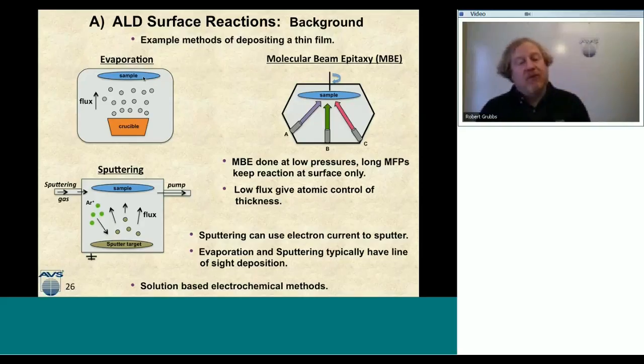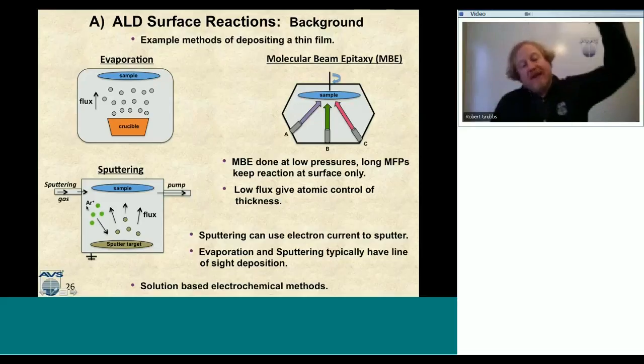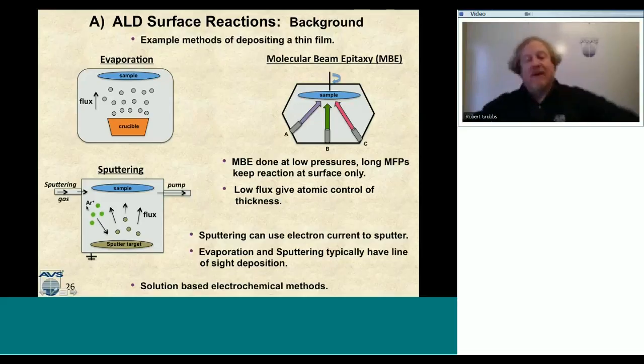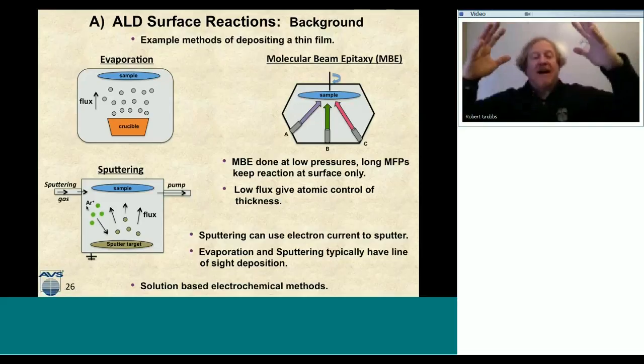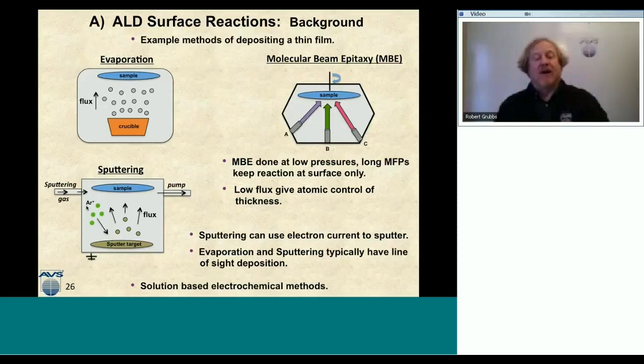Another similar method to that is sputtering. And sputtering is sort of a more aggressive method of evaporation, where we'll have a sample mounted on the top, and we actually have sputtering targets that are made of certain elements or compounds, and we bias those targets. And so we're going to use argon to accelerate the argon ions down to the sputter target, and then we're going to eject the material on the sputter target, and the flux of that will actually then redistribute itself on the sample.